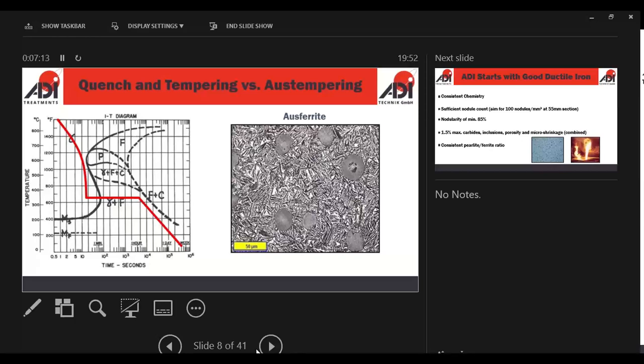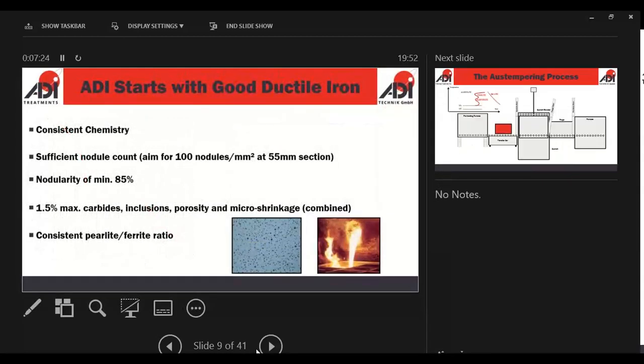Salt itself is a mixture of potassium nitrate and sodium nitrite, so both commonly available on the market, and they work together. When you put them together as a 50-50, they melt at about 150, so therefore we can use them between that 200 and 400 degrees centigrade.